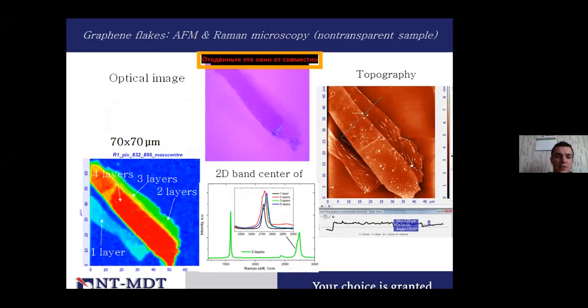So then from the same area, you can collect the Raman signal from the 2D peak, which is responsible to the number of the layers of the graphene. And you can see on the left that a color represent as the Raman signal, and the higher signal means bigger number of the flakes in this area. So you can see these combined measurements in the same time. When you measure topography and some Raman signal, you can understand better about your structure.